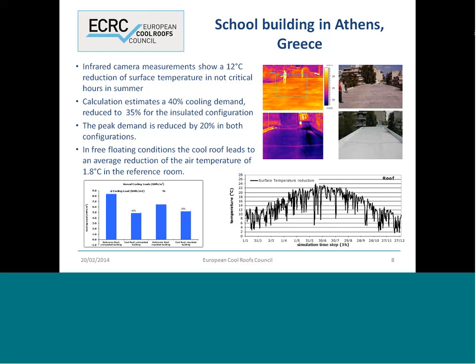The infrared photos on the right were taken before and after the cool roof application, at the same hour of the day, but of course on 2 different days, characterized in any case by very similar climatic conditions. The 2 photos were not taken during the solar peak, when surface temperature reached the maximum, but the temperature differences are still relevant. They are about 12 degrees.